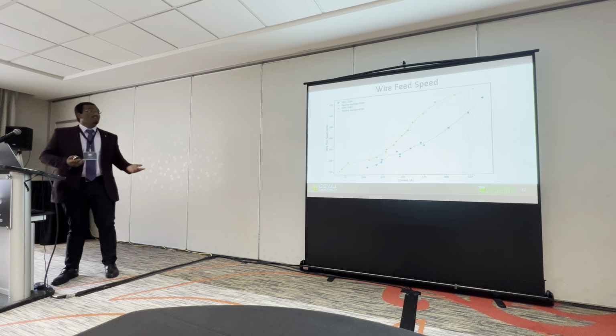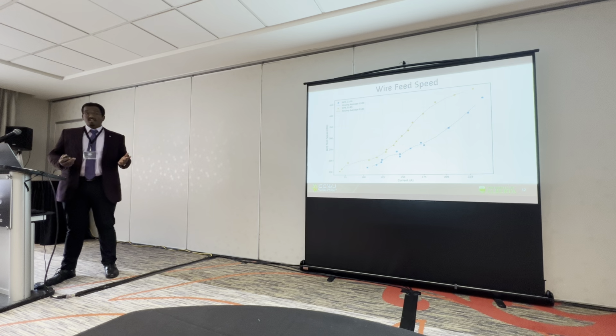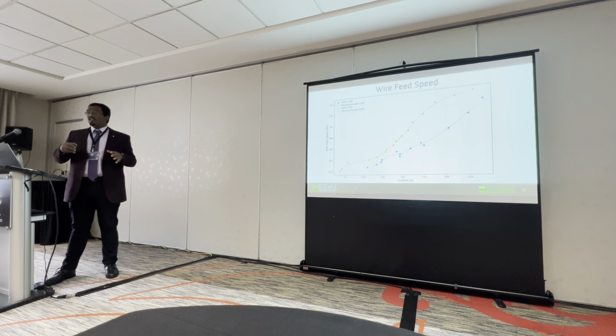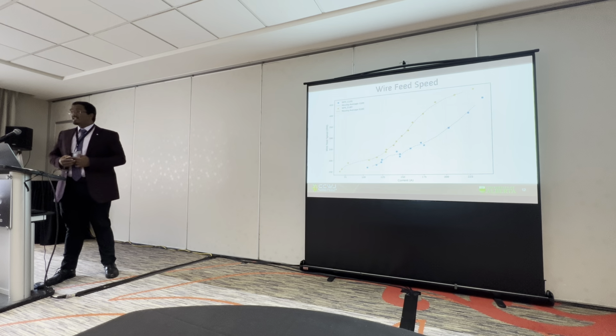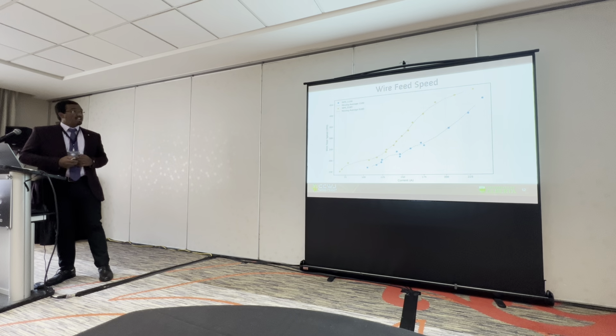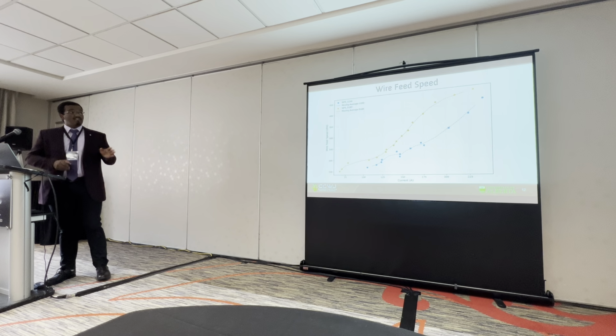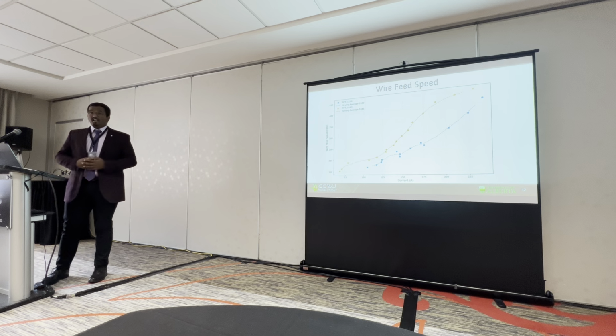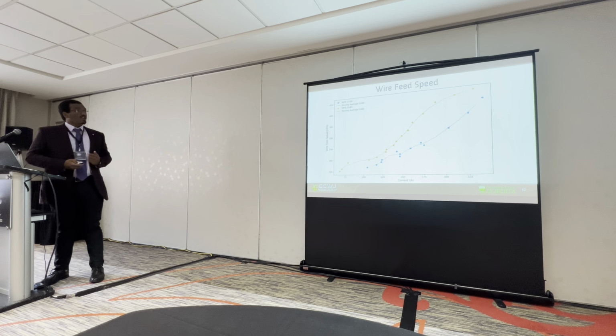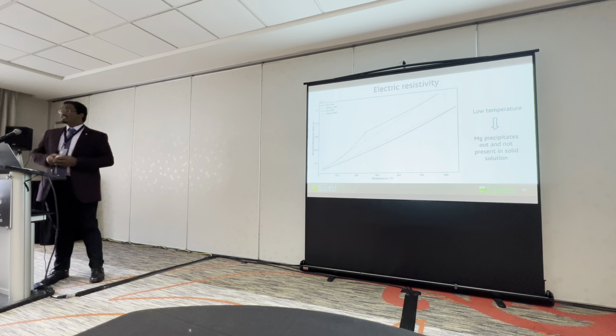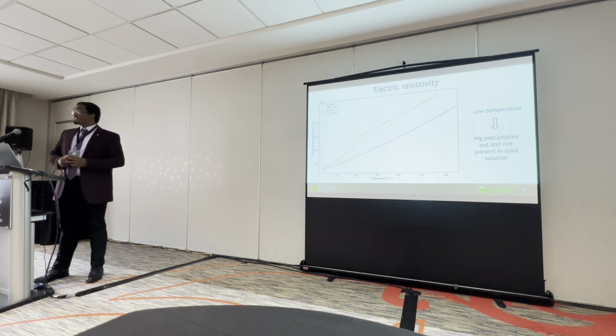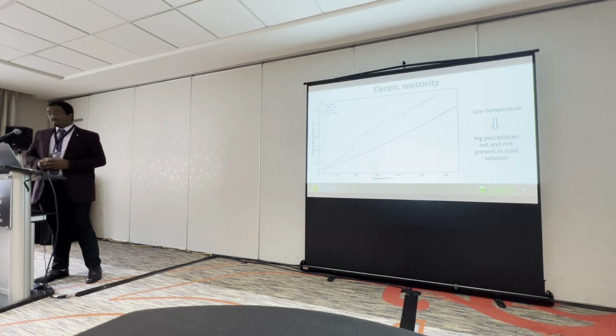So, next, the wire feed speed. We know that the wire feed speed of the alloy which contains magnesium, which is 5183, is supposed to be higher, and that's exactly what was measured. Here we had 5183, shown by the orange circles, tending to have a much higher wire feed speed than 1100 across the entire current range. Since it's expected, we're just moving on. Electrical resistivity: we also calculate the electrical resistivity for 1100 and 5183.